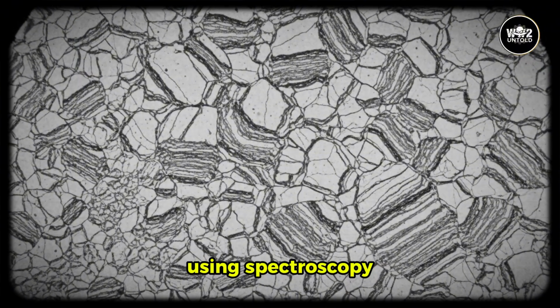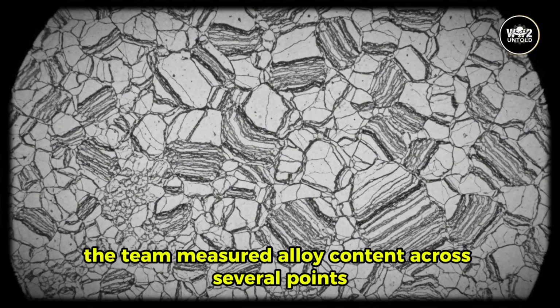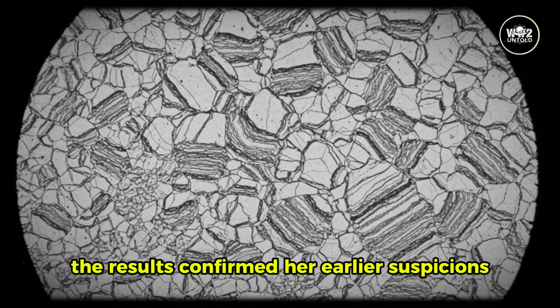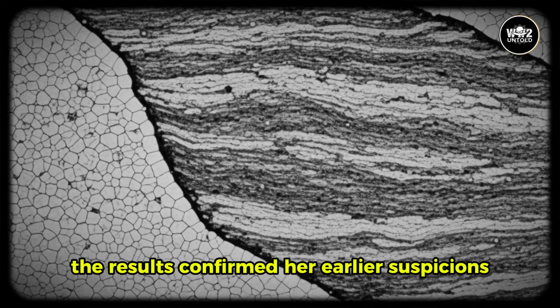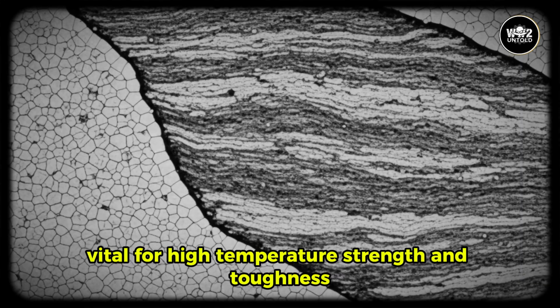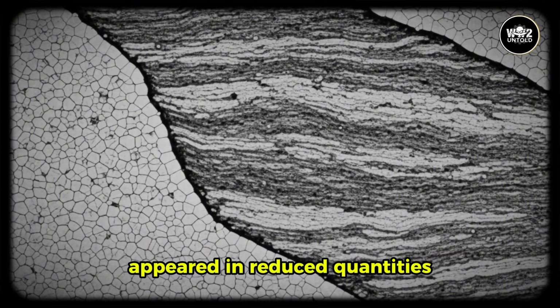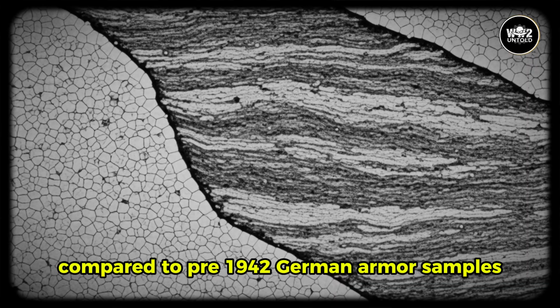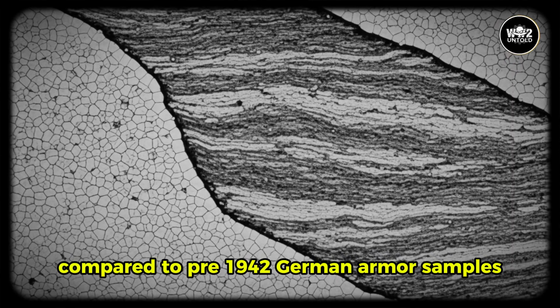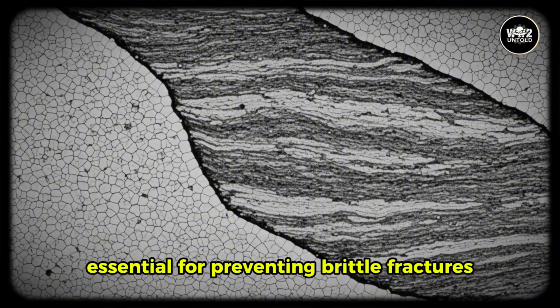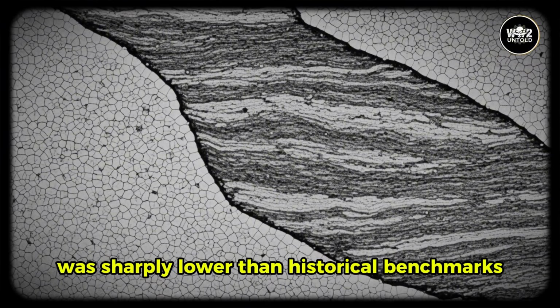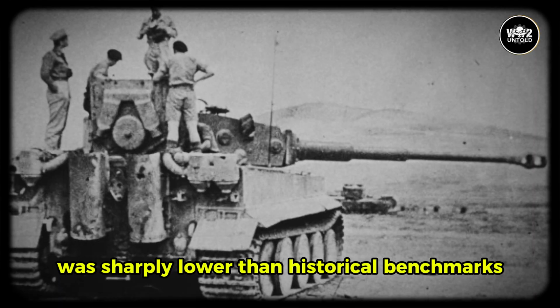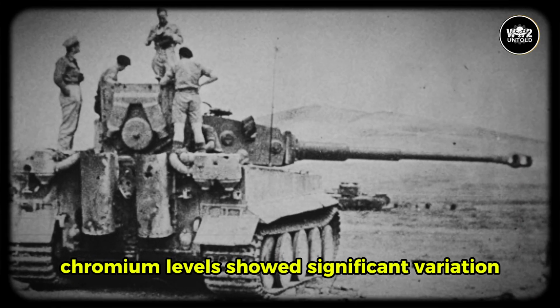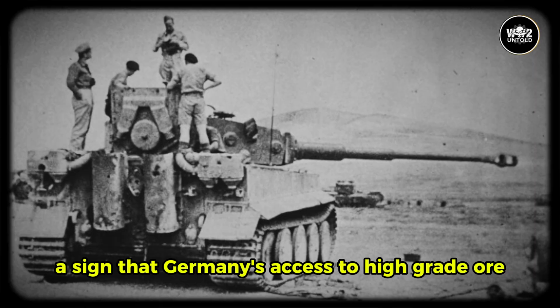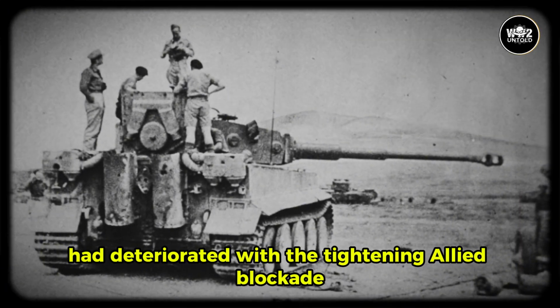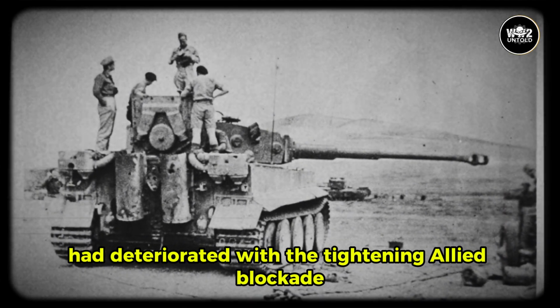Chemical composition analysis was next. Using spectroscopy, the team measured alloy content across several points. The results confirmed her earlier suspicions. Molybdenum, vital for high-temperature strength and toughness, appeared in reduced quantities compared to pre-1942 German armor samples. Nickel content, essential for preventing brittle fractures, was sharply lower than historical benchmarks. Chromium levels showed significant variation, a sign that Germany's access to high-grade ore had deteriorated with the tightening Allied blockade.